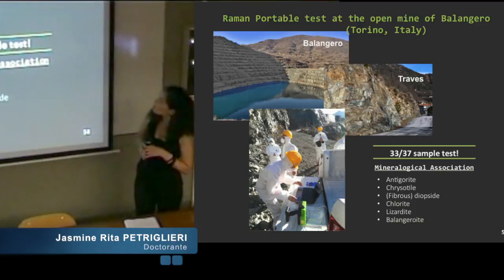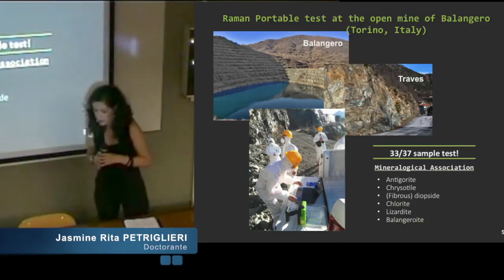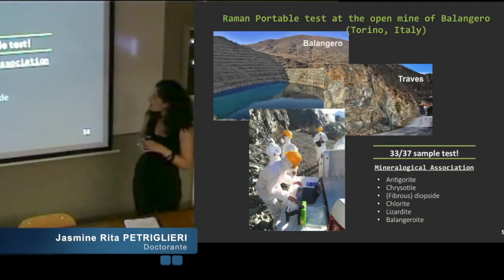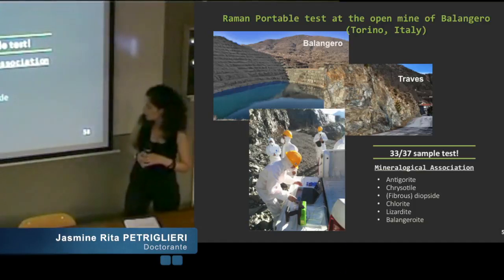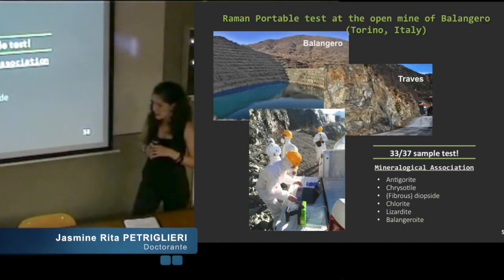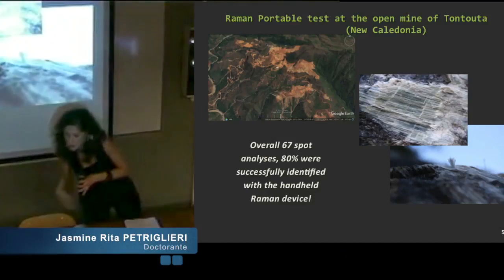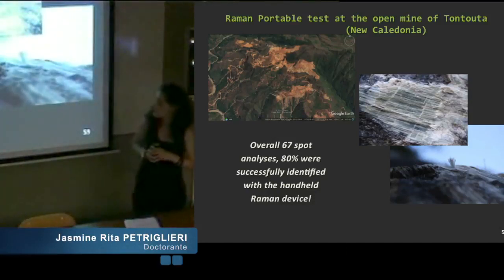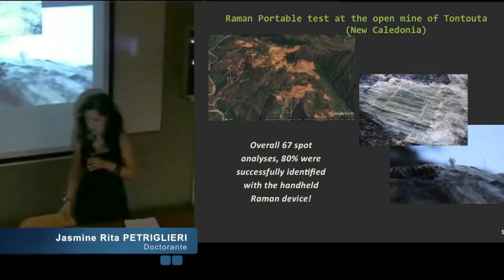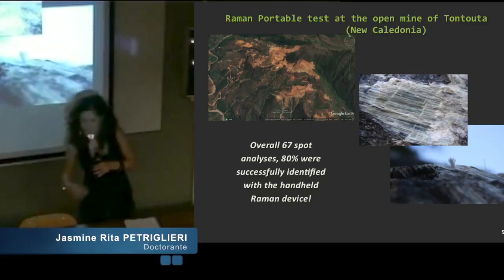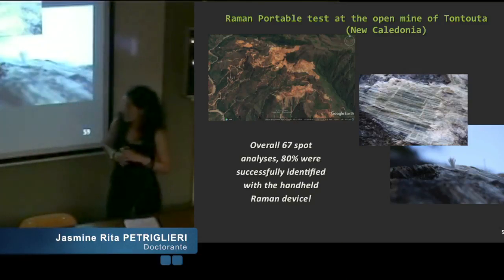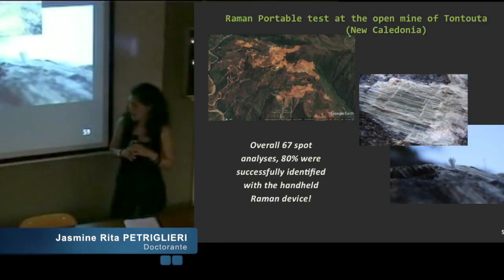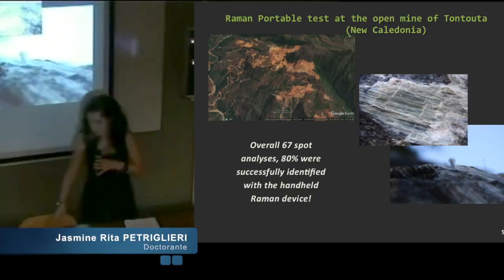So finally, the portable Raman was tested at the open mine of Balangero, near Turin, and on 37 sample tests, which means spot analyses, 33 allowed to identify the typical mineralogical association. The portable Raman was also tested in New Caledonia at the open mine of Tontouta, and in this case, on 30 sample tests, 20 gave a positive response, allowing to identify the mineralogical association. On overall analyses, 80% were successfully identified with the handheld Raman device.